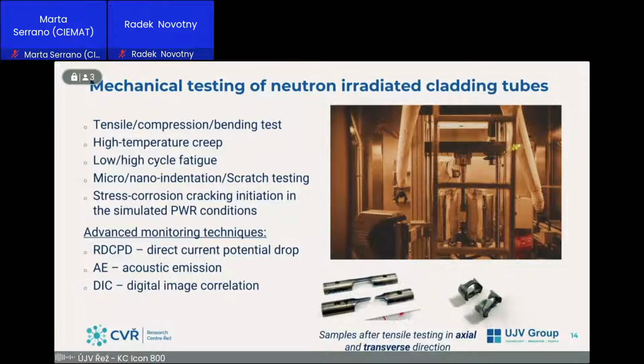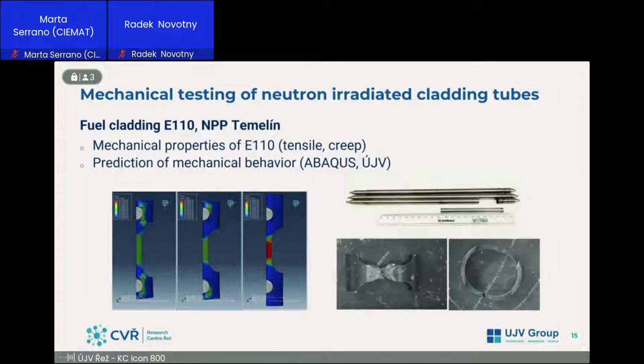So here is the insight to the hot cells, and there are the example of specimens after tensile testing in axial and transverse direction, which we perform on cladding tubes. So just briefly what we do, this is the project of testing of irradiated E110, which was irradiated from 1 to 6 years in Temelín. And then we do the mechanical testing like tensile and creep testing supported by electron microscopy to evaluate the radiation-induced damage. I will tell later. And we cooperate within the UJV group, where we compare the experimental data with the simulations. So they predict the mechanical behavior, and we cooperate with our experimental data.